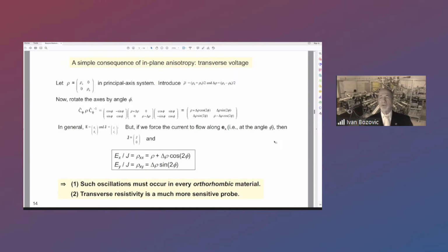And if you go through this trigonometry quickly, you will find that as you rotate the azimuth angle, the off-diagonal matrix element must oscillate with period pi. It means that they will have 4 nodes. And what you can also see from this expression is that longitudinal resistivity oscillates around some average value. And if the amplitude of this oscillation, delta rho, is much smaller than rho, the average value, then this oscillation may be buried within the noise. Because when we measure a lot of different devices, let's say in different angles, then inevitably there is some device-to-device variation due to lithography, etc.